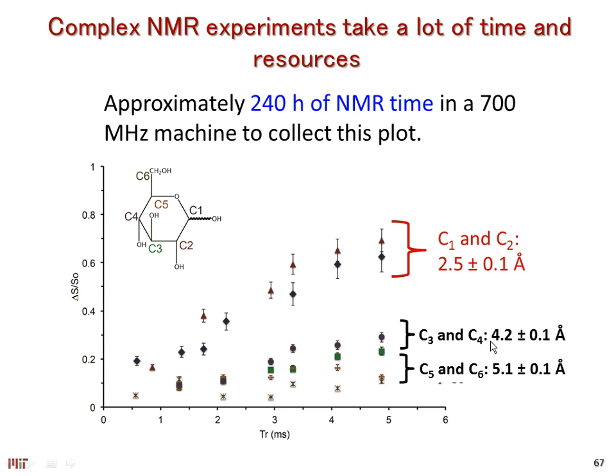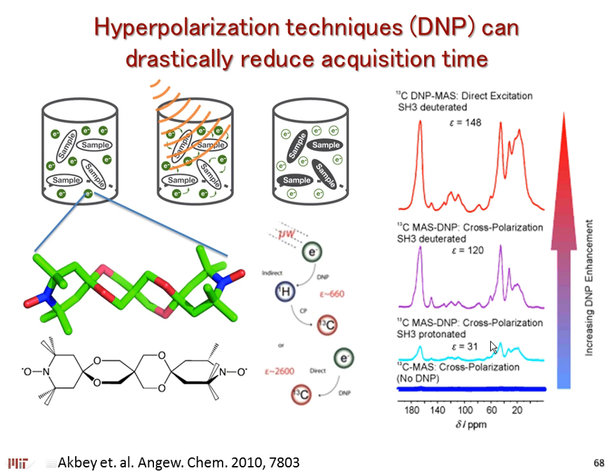NMR is a very powerful technique, and we start looking at what else we can do to decrease these acquisition times. Something that we have been exploring also with Bob Griffin is the application of what are called hyperpolarization techniques, such as dynamic nuclear polarization, or DNP. For those of you unfamiliar with NMR, or if you are familiar with a technique such as CP, or cross-polarization, you can think of DNP as cross-polarization on steroids. You take microwaves, you have a biradical, such as this one over here, you polarize it with microwaves, and then this polarization can get transferred to the nucleus of choice, or to a solvent that has protons, and then you can transfer this polarization back and forth, and you can enhance the signal in your NMR quite a bit, reducing acquisition times by a lot.